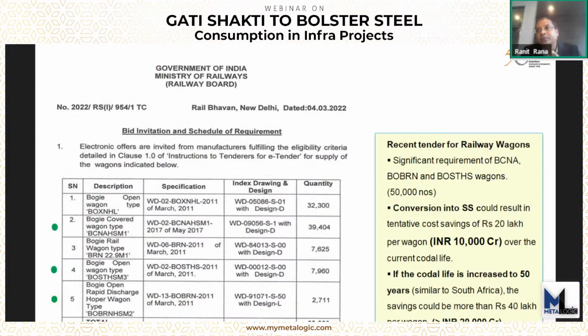And if we extrapolate these findings to the recent tender which the Railway Board had floated about 2 weeks back, out of 90,000 wagons, almost 50,000 wagons are in carbon steel. And these are basically the covered wagons in carbon steel, the bottom discharge wagon, the BOST wagon, and the box wagon. Now, if these wagons could be converted into stainless steel, then there is a tentative cost savings of approximately 20 lakh per wagon, which translates to 10,000 crores over the current codal life.